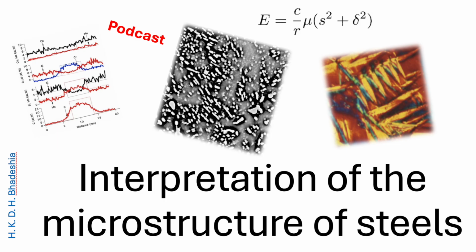Think of this as the civilian path. The civilian path, the relaxed, patient path. Precisely. This mechanism requires physically breaking and then reforming atomic bonds, so it involves a lot of diffusion. Meaning the atoms have to actually move around. They have to be mobile enough to diffuse over distances comparable to the size of the product that's growing. And because they're diffusing freely, this is the path that avoids high strain energy. But, and this is a big but, it naturally leads to chemical partitioning.